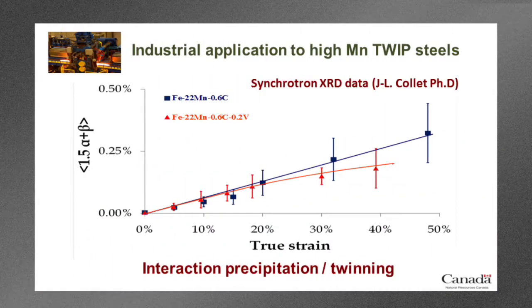Now we tried to investigate that, so we went to the synchrotron. This was work done by Jean-Louis Collet during his PhD. And what we were looking at here, this parameter alpha plus beta that we're plotting, is essentially related to the number density of stacking fault or twinning planes in a certain direction, in the 110 direction in the austenite. And we're plotting that against true strain for two different alloys. One would be the reference alloy with no vanadium in it, and one would be the alloy with 0.2 vanadium, and that's the red curve, and the blue curve is the reference one.